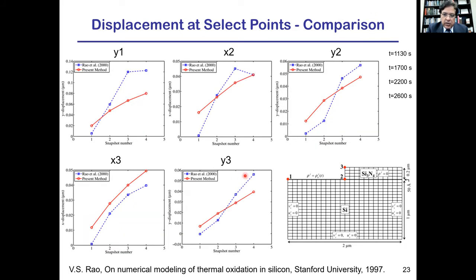This slide shows the X and Y displacement at these points 1, 2, and 3. For example, here we have a snapshot of the vertical displacement at point 1. Red are our results and blue are the results in the reference. We get a good correlation. However, the two material models are different, so we see some variation, but overall the response of the two models is fairly consistent.